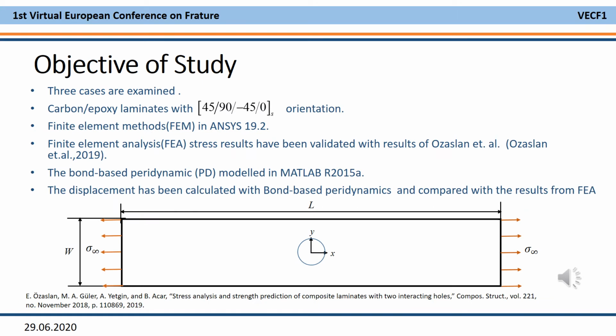Three cases are examined. One is with one hole to the free edge, and the other two are interactions between two holes separated by several distances. The material used is carbon epoxy laminates with the orientation given. Stress and displacement calculations have been done with the finite element method in ANSYS. The finite element analysis stress results have been validated with results of Ozaslan et al.